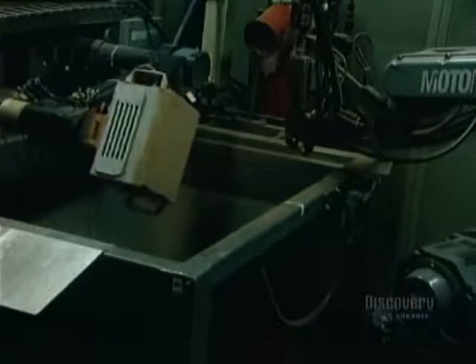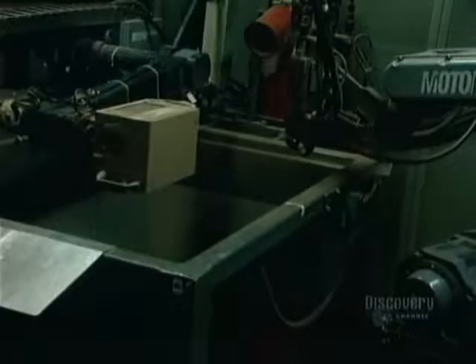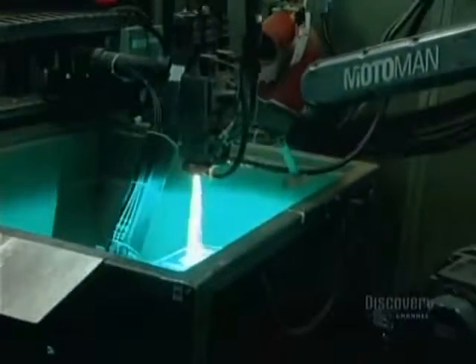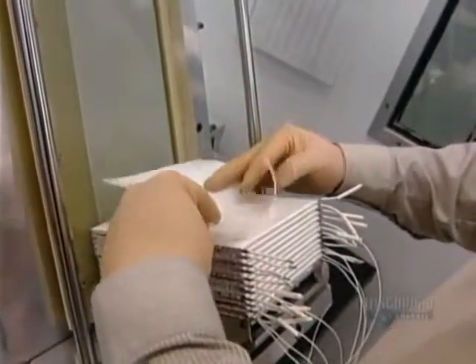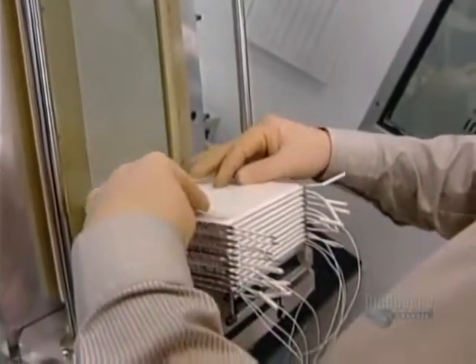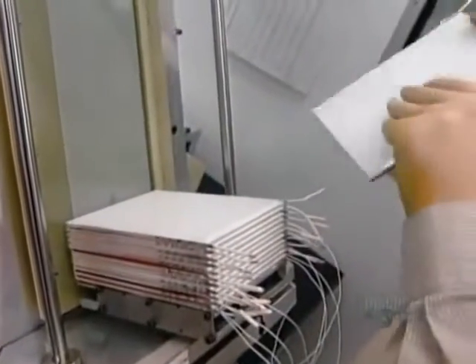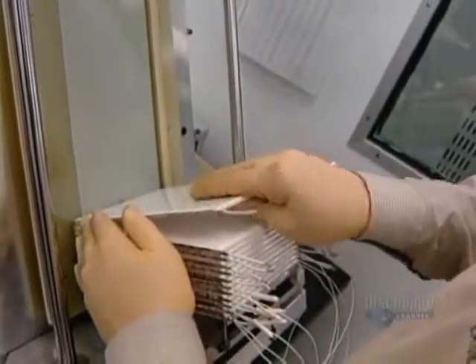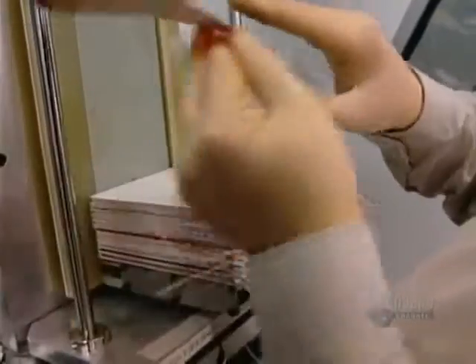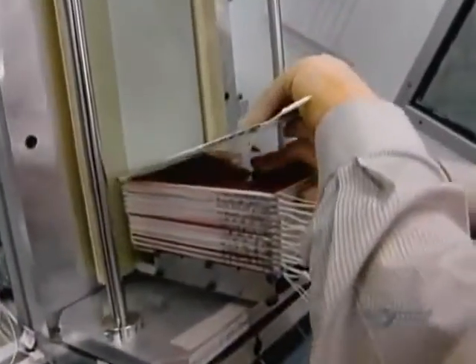It comprises 4 elements: lithium, which acts as the anode, a metallic oxide cathode, a dry solid polymer electrolyte, and a metallic current collector. All that remains to be done is the assembling of the individual battery cells into a module. It begins with the placing of individual cells onto one another and isolating them with foam so that they don't touch each other. These red sheets are actually heating elements since the lithium metal polymer cells function at temperatures of between 40 and 80 degrees centigrade.